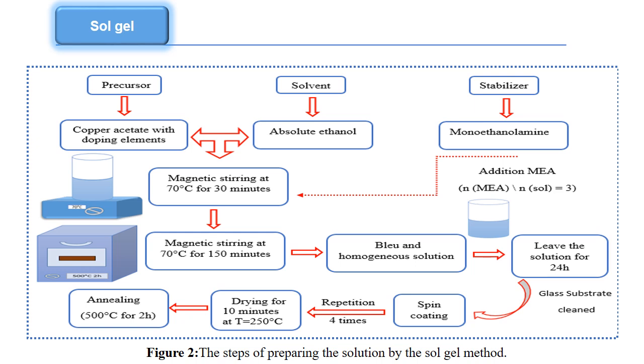Sol-gel spin coating method. Thin films of copper oxide, undoped and doped with zinc, were elaborated by the sol-gel spin coating method on a glass substrate, using an acetate precursor with the doping element dissolved in ethanol with a molarity of 0.2. In the end, we calcined our films at 400 degrees Celsius for 2 hours.